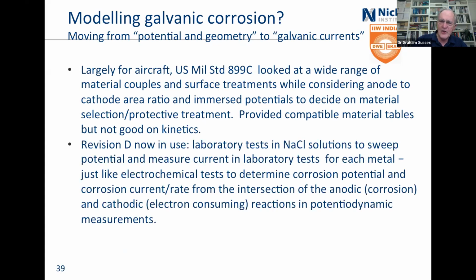That revision D, which is now in use, it's only been out for a little while, they used laboratory tests in sodium chloride solutions to sweep the potential, and that is a laboratory test. You basically start from the cathodic side, so it's not going to corrode, and you sweep through and measure the potentials. And you can actually then do electrochemical calculations and work out what's going to happen. And you can then look at a whole series of treatments.